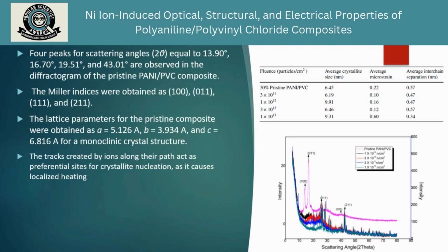The lattice parameters have been obtained using the FullProf program, and were found to be 5.126 angstrom, 3.934 angstrom and 6.816 angstrom for a monoclinic crystal structure. Average crystallite size, microstrain and interplanar separation for the samples have been obtained using the standard formulas and are reported in the table. It has been observed that the crystallite size has increased with irradiation, again corresponding to the cross-linking produced in the samples.